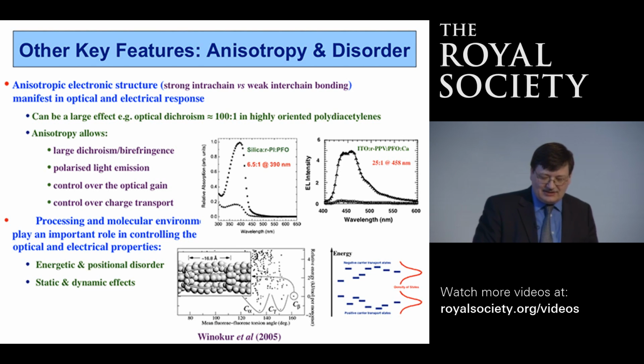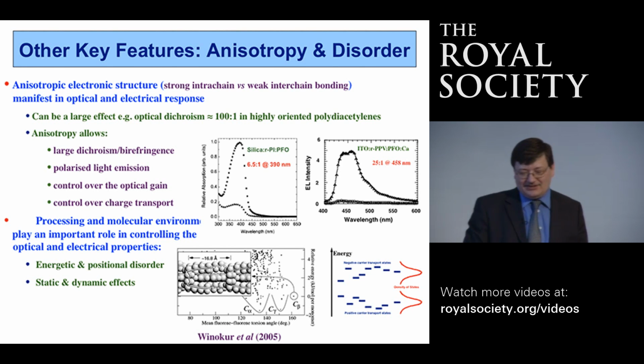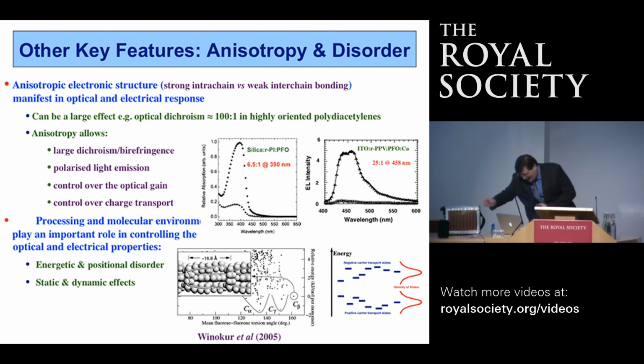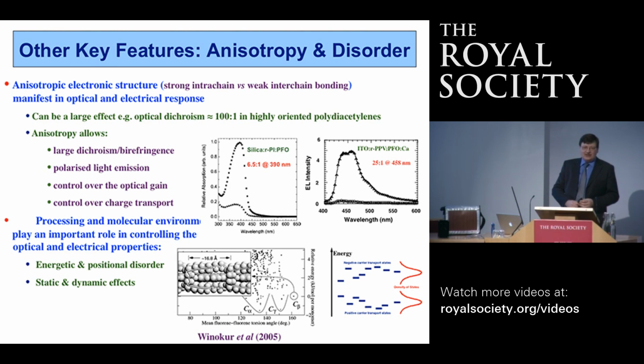Now, another feature is that typically these materials are disordered. And here's our disordered material, just a nice pile on the table. And that disorder gives rise to a broadening of many of the optical features. It gives rise to, again, effects in terms of transport. And perhaps the easiest way to think of that, using our rubber sheet analogy, is that we have a rubber sheet that's become a little bit worn in some places and a little bit thicker in other places. And therefore, the amount by which we get a distortion of that rubber sheet varies across the surface. And so basically, there is a distribution of energies within that system if we're moving the charge around. Sometimes it will sink in more, sometimes it will sink in less. And we see that when we look at the transport through these materials.